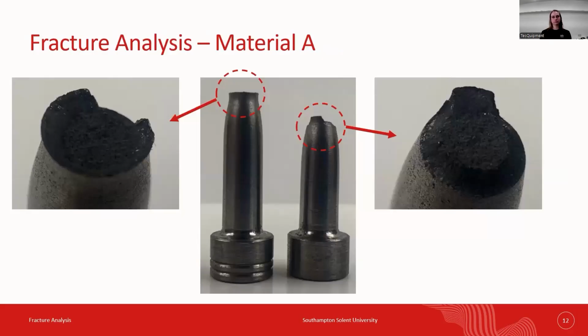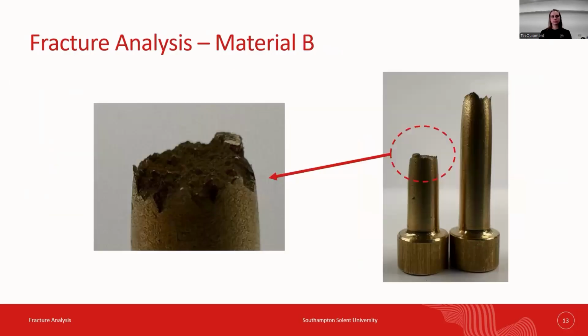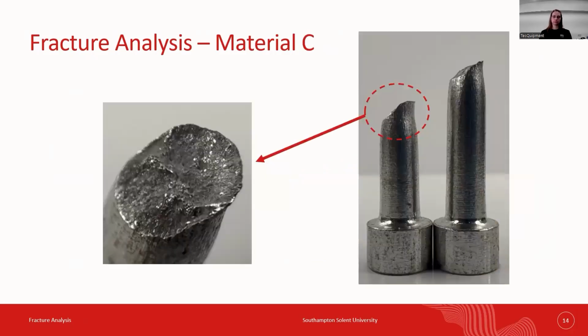In material A, we observed a classic cup and cone fracture, which is a clear indicator of ductile failure. In material B, a faint cup and cone shape is present, but it's much less pronounced than in material A. The tooth-like features around the edge suggest a mix of ductile and brittle behavior. This aligns with the properties of brass, which has moderate ductility, but can fracture more abruptly under certain conditions. In material C, the break shows a distinct angled shear plane and relatively clean surface, with little necking. This suggests a relatively brittle failure under shear. Even though aluminium is generally considered ductile, the behavior can be influenced by work hardening or surface flaws in the sample.